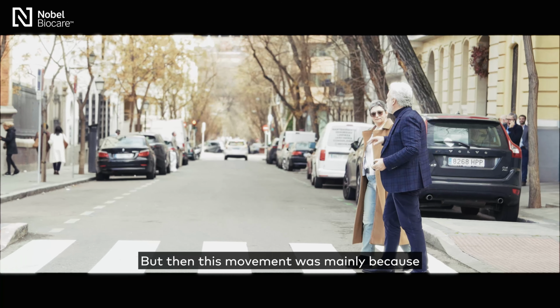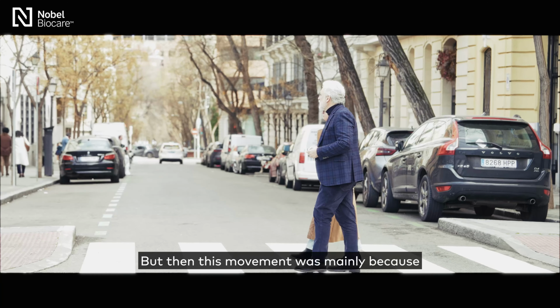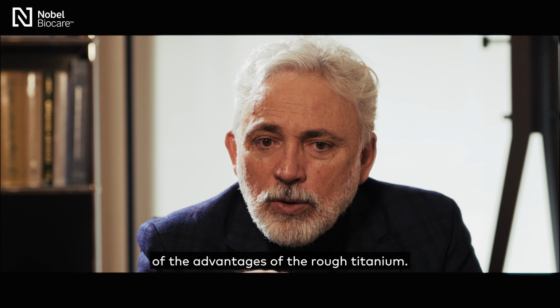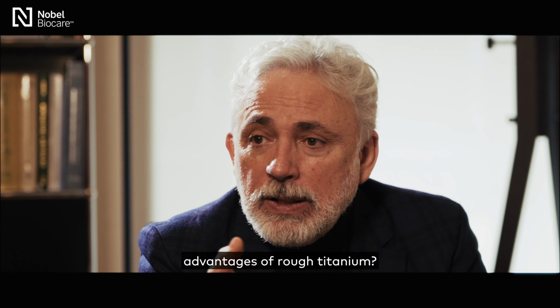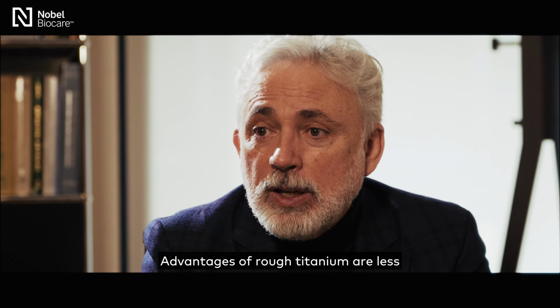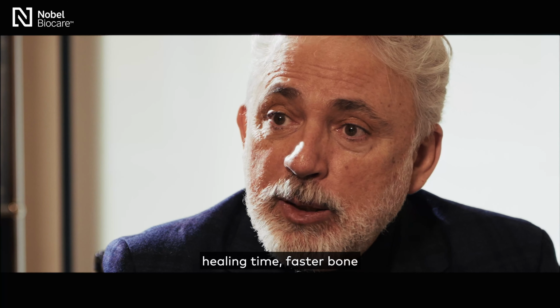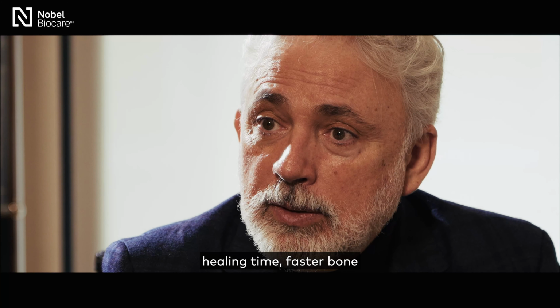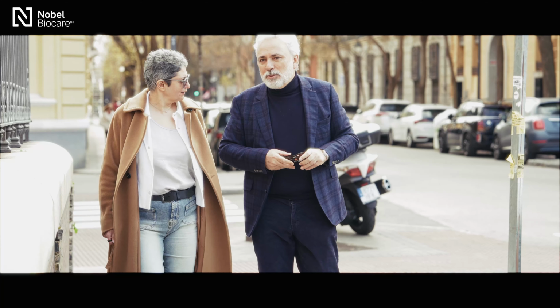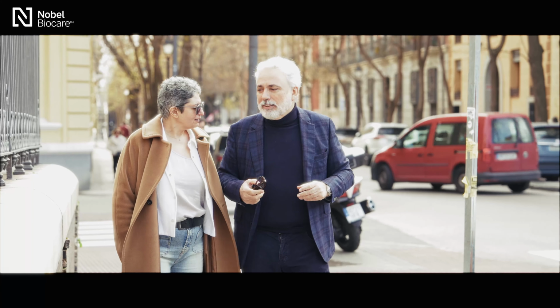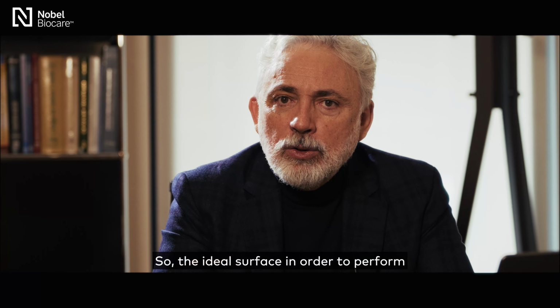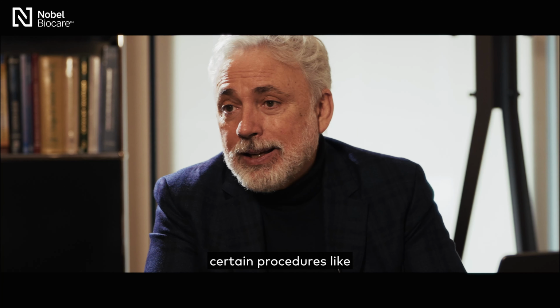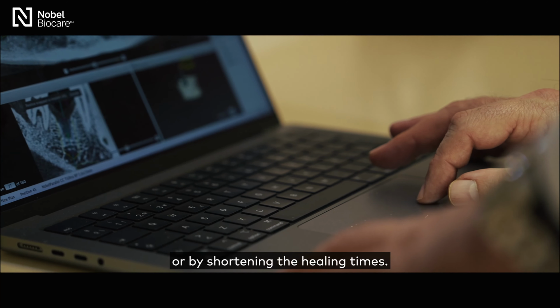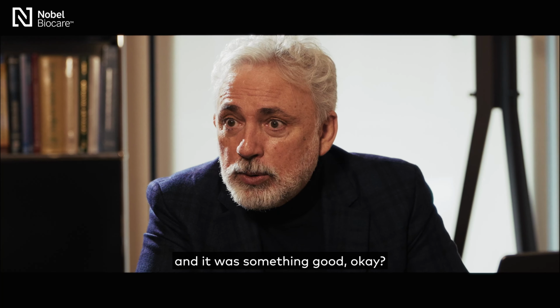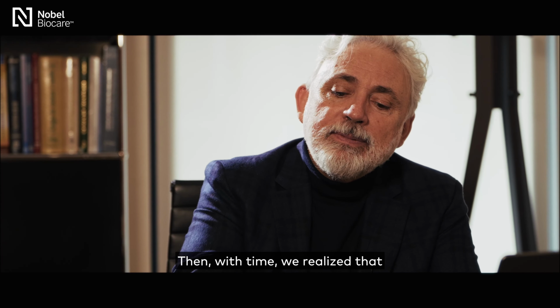But this movement was mainly because of the advantages of the rough titanium. And which are the advantages of rough titanium? Less healing time, faster bone growing on top of the surface, more bone-to-implant contact. So it's the ideal surface in order to perform certain procedures like immediate loading, for instance, or by shortening the healing times. This was something desirable, and it was something good, okay?